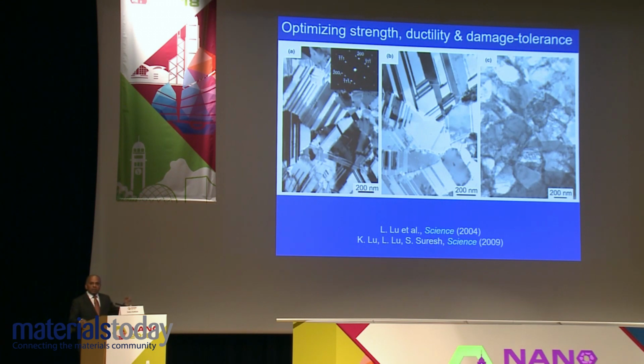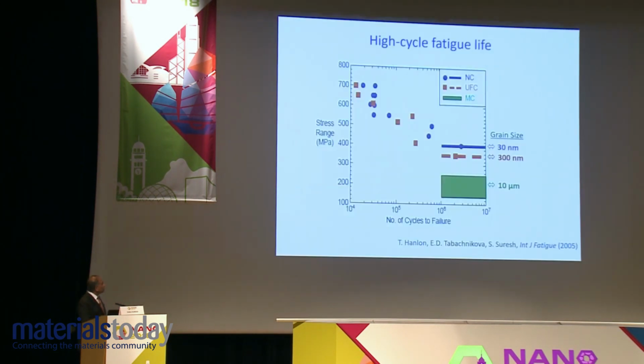So if you compare the 3 cases, obviously with very finely spaced twins, you get the highest strength. You also can have the opportunity to get higher ductility and even some beneficial fatigue properties. But there are other artifacts of this. The activation volume of these materials is very different than conventional materials. And the other interesting result that comes out of this is the twin spacing in these nano-twin microstructures has an effect that's very similar to grain size effect in nanostructured materials, nanostructured metals. And so this is an example of one strategy that has been used among many, and I'm not going to go through all of these strategies.